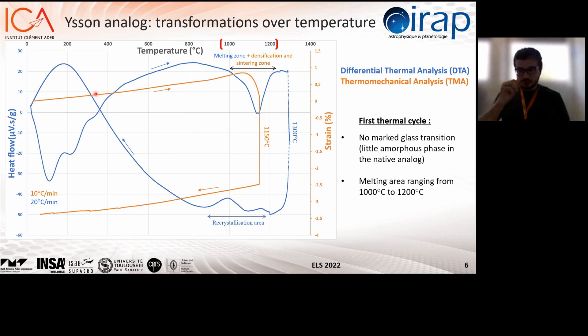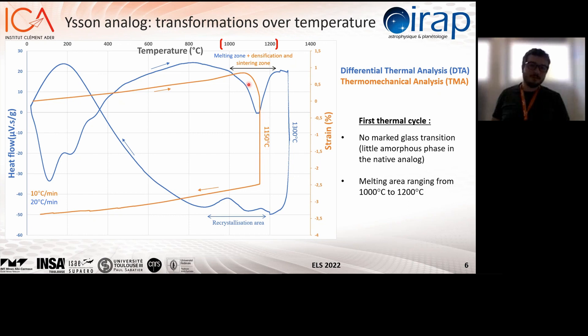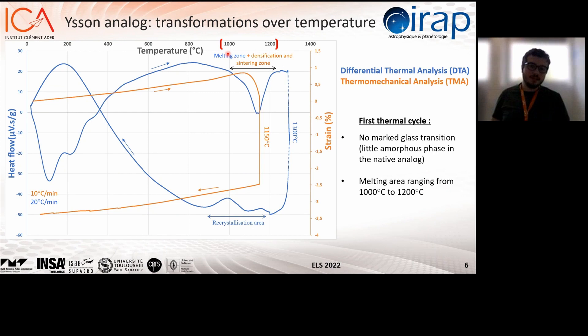The orange graph shows the result of a thermomechanical analysis, used to track the expansion of a powder over temperature. In the first part of the graph, the slight increase in strain is due to thermal expansion, but it's quickly hidden by a sudden decrease in sample length, which indicates that the powder has begun to agglutinate or sinter. These results show two things: first, we need to be at least around 1000 degrees if we want to do anything; and second, there is no amorphous phase in our initial analog.